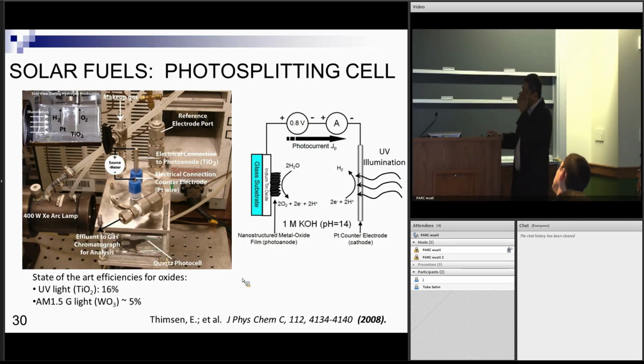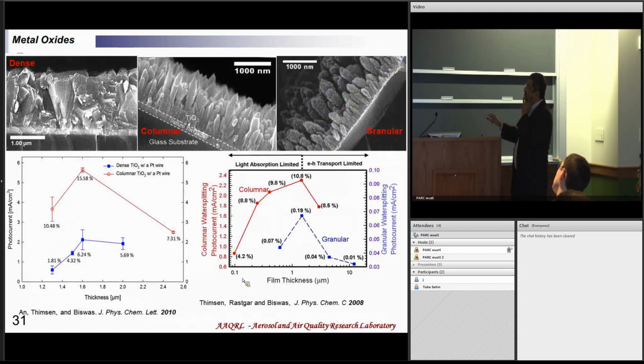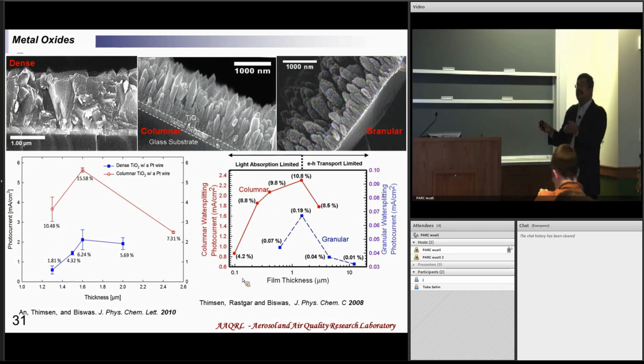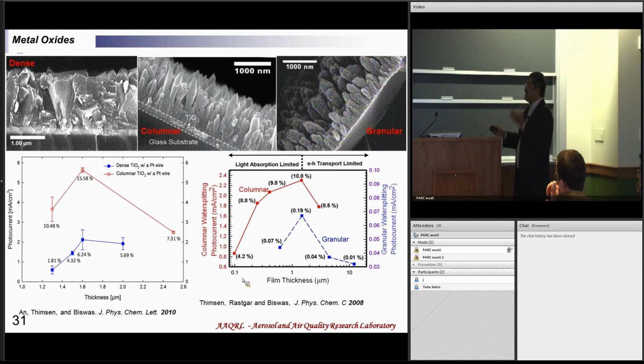So I can make these different morphologies, and I want to study the effectiveness of these, and I'll just show you some results. Here is the water splitting photocurrent. So I put it into this device and shine light, and I can measure the photocurrents, and I plot this as a function of film thickness, and you can see the columnar films are much more effective than the granular films for the reasons that I quoted. And this is an actual test of these different structures, and of course these solid films are the least effective. The granular films at least are partially effective, but the columnar ones are more.